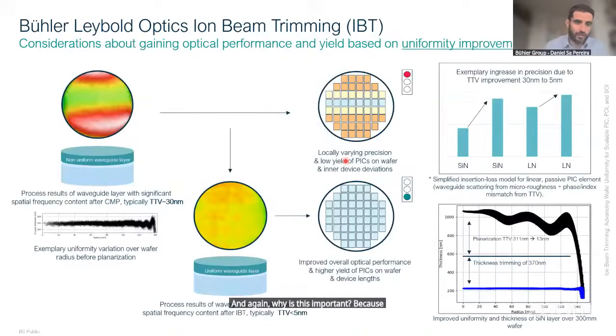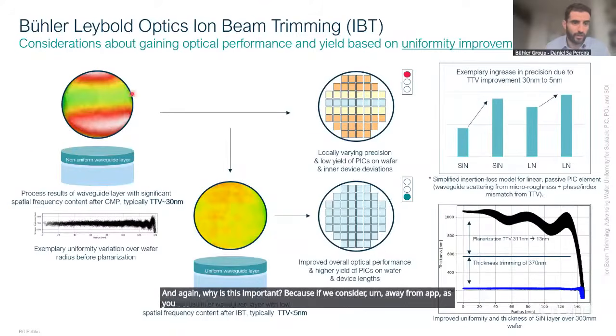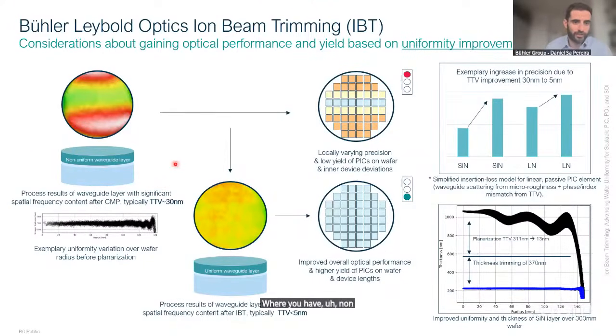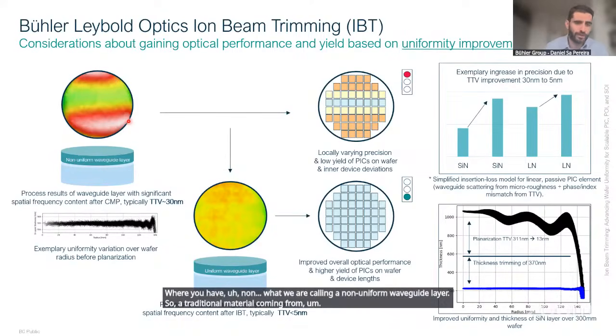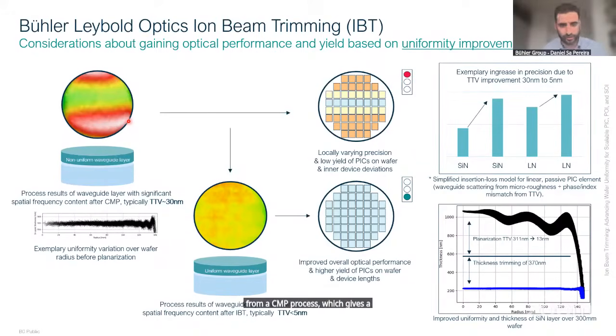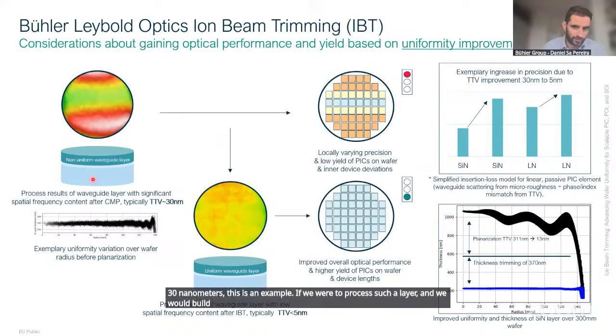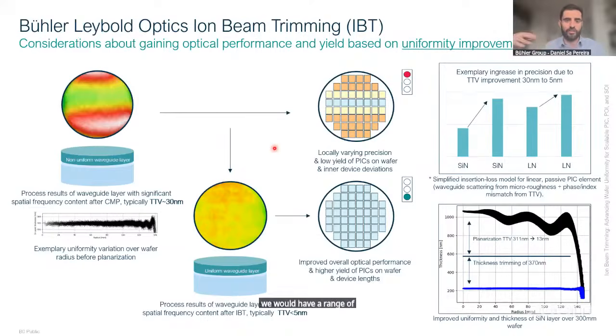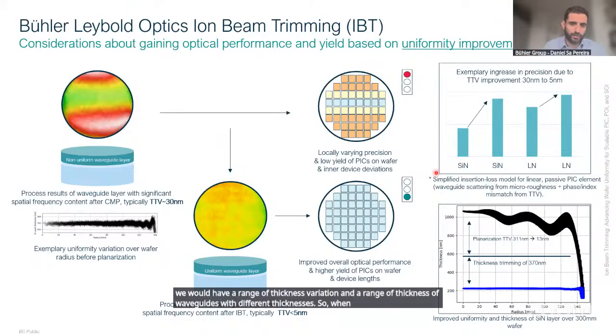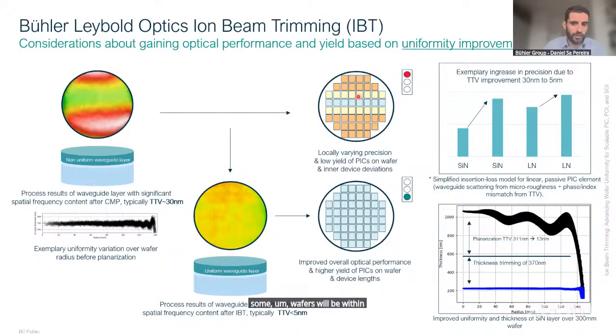Because if we consider a wafer map, as you see here on the left-hand side, where you have what we are calling a non-uniform waveguide layer. So a traditional material coming from a CMP process, which gives a TTV, or total thickness variation, of about 30 nanometers. This is an example. If we were to process such a layer and build the waveguides and the actual devices out of it, we would have a range of thickness variation and waveguides with different thicknesses. So when we look at the yield on the wafer level, some wafers would be within spec, but some of them would be out of spec.